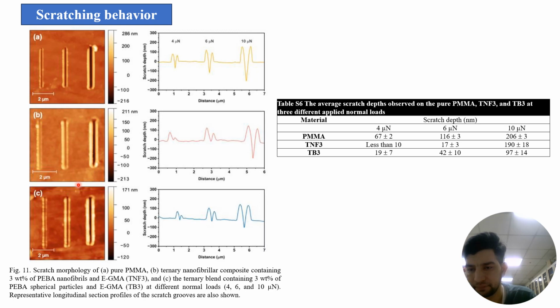So the scratch depth on the TNF3, this is pure PMMA, this is TNF3 and this is TB3. The scratch depth observed on PMMA was recorded as 67, and this is recorded as 67 plus or minus 2 nanometer at 4 micronewton. The scratch depth of TNF3 and TB3 were lower compared to PMMA under low normal load, at 4 and 6, indicating an improved scratch regime.